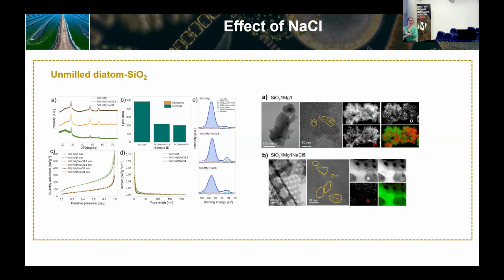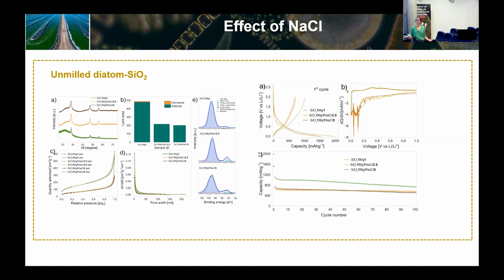So if you don't add any sodium chloride and you just do the reduction, thinking that everything will go well, then you find that particle morphology is totally lost, meaning that there is some heat building up in the reactor that affects the morphology of the particles. So we had to add more sodium chloride to keep the material morphology. Once we fixed the sodium chloride content, we went to some electrochemical results.